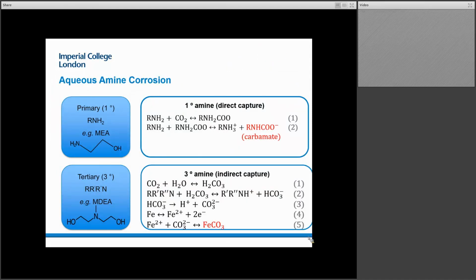So the nominal background required to understand is that amines don't behave the same way in the presence of CO2. Primary amines, like the one shown, MEA, react in a direct capture mechanism, and that's advantageous in some ways. The reaction is quite quick, but it requires a 2-to-1 ratio. So it costs more than we would like, and it produces carbamates. By contrast, tertiary amines, which are actually more popular for natural gas sweetening, react in an indirect method. But the stoichiometric ratio of 1-to-1 is far more desirable. But what's interesting about this amine is that we produce bicarbonate and carbonate as a part of this process.